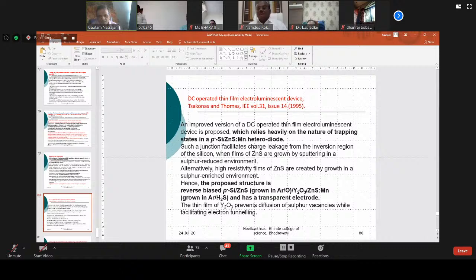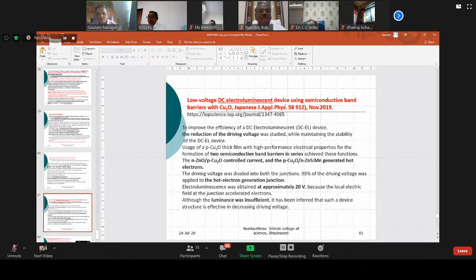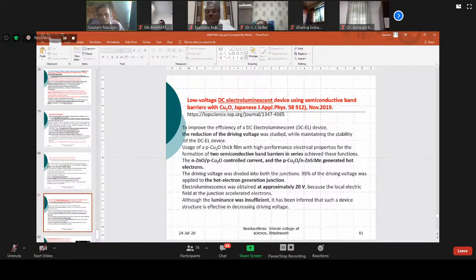The proposed structure is reverse biased P silicon zinc sulfide grown in argon oxygen and yttrium oxide zinc sulfide. These are the composite actually. Argon H2S grown and there's a transparent electrode. Okay. And then low voltage, this is a recent one. Low voltage DC electroluminescent device using semiconductive band barriers with copper oxide. This is a Japanese report. No other report is there. Where they have done the reduction of driving voltage. They have done it while maintaining stability.